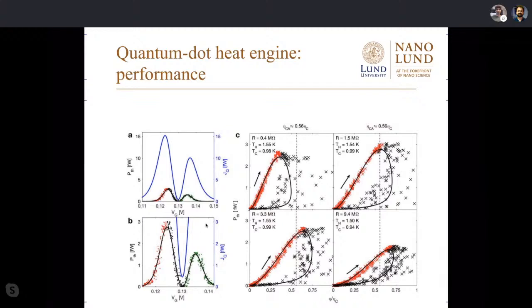And now, this is a different type of plotting the current. This is now plotted as power. We know our voltage, so from the current, we can easily calculate the power. And you can see that the quantum dot produces finite power on either side of this resonance, more on one than on the other. This has to do with spin degeneracy. So this is nicely reproduced by the model as well.